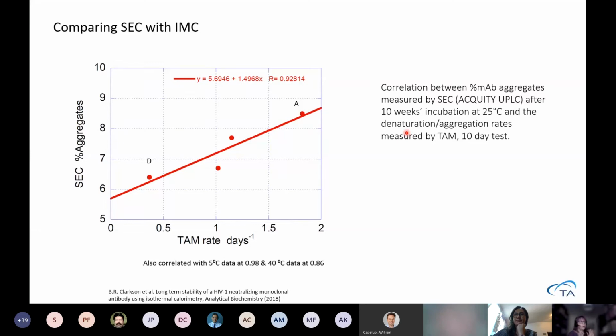So we can also conclude we have a correlation, but the size exclusion has been done in 10 weeks and all the TAM tests have been made in 10 days. So for ranking and seeing better or less good buffers, it's much quicker to do this with, I say TAM, the isothermal microcalorimeter that's used for this. So that's the name of our calorimeter.